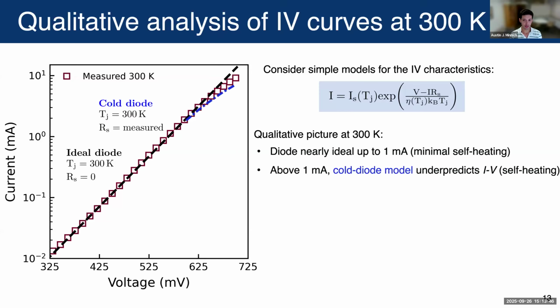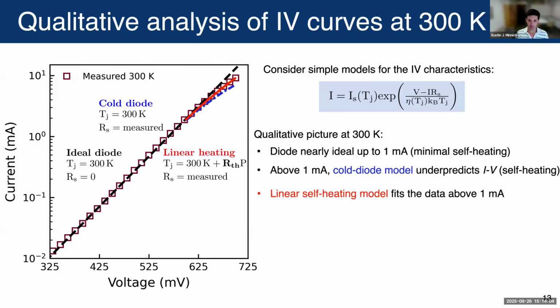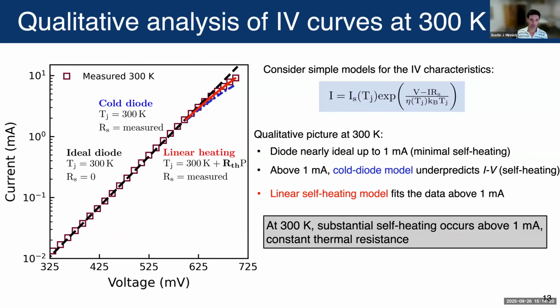Let's improve the model by accounting for series resistance, which we can measure. And if we include that, we actually overcorrect with that dashed dotted blue line. So now we underpredict the measurements. And then finally, we can try to fix that by accounting for self-heating. And if we assume that the junction temperature is linearly depending on the applied power, we get the red line with the R thermal as the fitting parameter, and that fits very nicely. So we conclude that at room temperature, we see self-heating is evident in the data above a milliamp or so, and that the thermal resistance is independent of the bias.